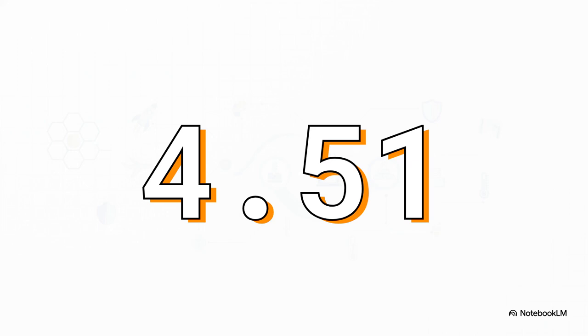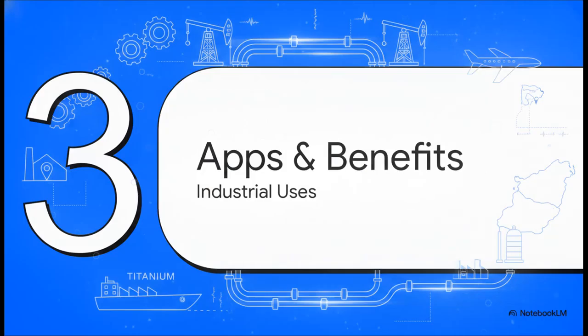This metal boasts a massive 1,660 degrees Celsius melting point. To put that into perspective, that is literally hotter than the lava flowing from most volcanoes. It also delivers a tensile strength spanning 345 to 480 megapascals, a minimum yield strength of 275 megapascals at a 0.2% offset, and a 20% minimum elongation. This unique combination of incredibly high tensile strength and extremely low density is exactly why this material is used to build rockets. Section 3. Industrial applications and benefits.